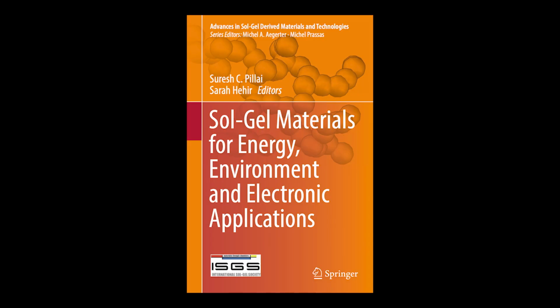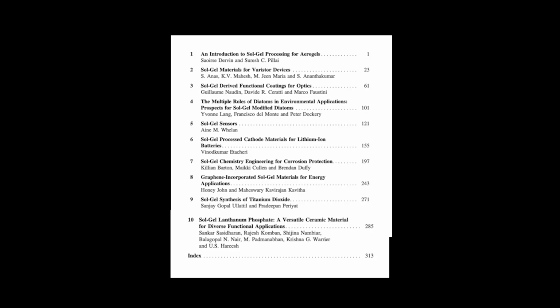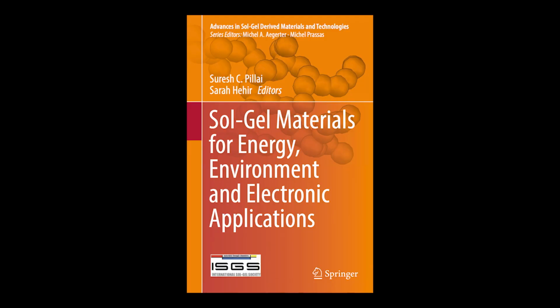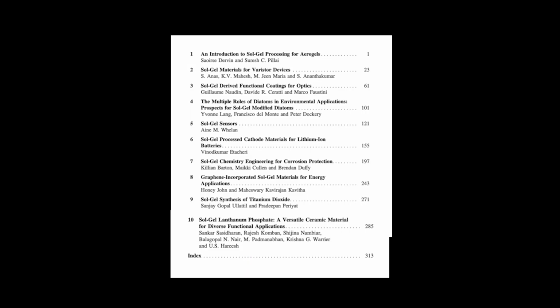Interesting shape. And similar to TiO2, this ceramic also undergoes structural transitions upon heating. It does, yes. But its final high-temperature state is immensely robust. LaPO4 typically starts out in a hydrated form after synthesis. Upon heating, it transitions to an intermediate hexagonal crystal phase around 400 degrees C. Then, as you heat it further, it converts completely into its final thermodynamically stable monoclinic phase by about 1200 degrees C. And it's this monoclinic phase that's so valuable. Right. It's reported to be stable well above 1900 degrees C, and it possesses incredibly low thermal conductivity. The chapter quotes just 1.30 watts per meter Kelvin at 1000 degrees C. That makes it an excellent candidate for high-temperature thermal insulation or barrier coatings.